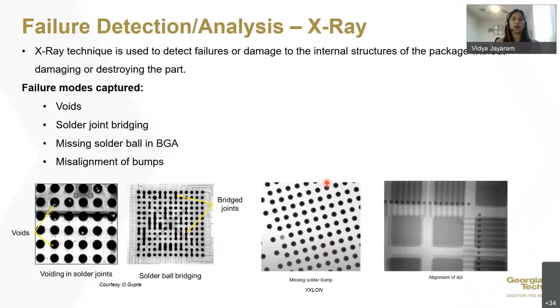Moving to X-ray. X-ray is a common technique that's used to detect failures in a non-destructive manner. It can detect damages to internal structures of the package. The main failure modes that are captured through X-ray are voiding, bridging, missing solder ball, or misalignment of the bumps, as you can see in these images. X-ray, I think, is a pretty effective non-destructive technique to capture these kinds of defects.